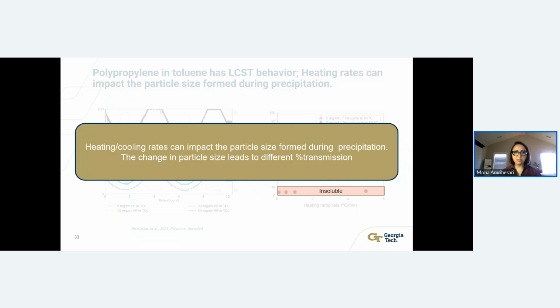So far we compared two systems of LCST and UCST behavior when we observed the change of the transmissivity with the particle size. And we concluded that there is an impact on the particle size forming during the precipitation. So the change in the particle size also leads to the change in transmissivity. But since the change was not very statistically significant, we went with 0.5 degrees C per minute to not have very long experiments compared to 0.1, but also be able to give the polymer enough time to catch up with some of the changes. And I will show in a few slides why this is very important for large molecules.